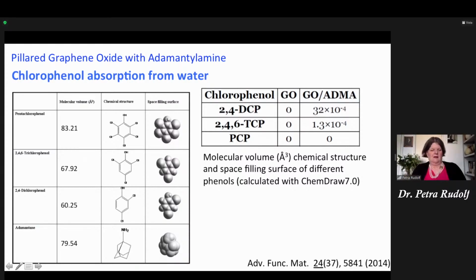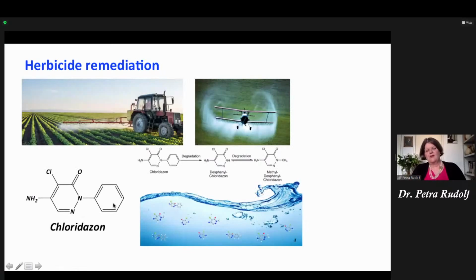So one can trap the molecules if one adapts the size of the pore to the size of what you want to trap. Of course, this is also useful for herbicide remediation, but here we do a different trick. So this herbicide here, chloridazon, has been used enormously in many parts of Europe because it was used in agriculture, because people thought that it was harmless or relatively harmless. But the problem is that it doesn't degrade. It just breaks up, and this is still aromatic pollutants, and they stay on for years and years. And in many parts of Europe, the concentrations are now reaching levels where one cannot neglect it anymore.